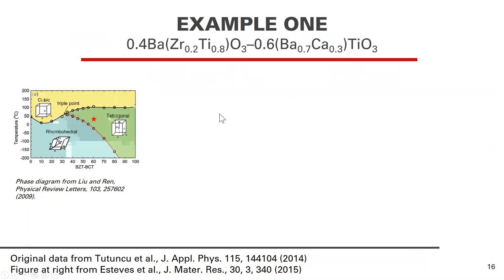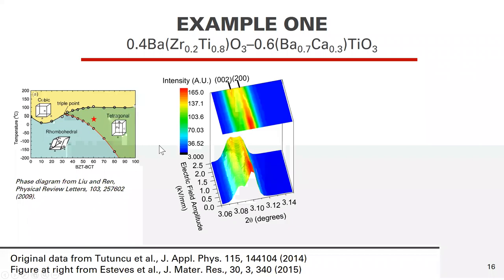Let me show you a few examples of how this is useful. There's a phase diagram of BZT-BCT here, one of the leading material systems being discussed in lead-free research. And we've done several experiments on compositions throughout this phase diagram, but the one I want to share with you today is represented by the star in that location of temperature and composition. If we take one of these compositions, which is tetragonal and not at the MPB, but close to the MPB, and we apply increasing electric fields, you can see in the raw data that we have an intensity interchange between the 002 and the 200 very clearly, right?